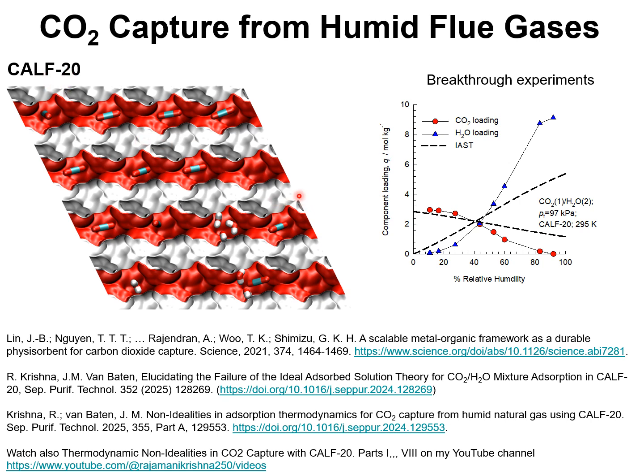CALF stands for Calgary Framework. Furthermore, we note that for percentage relative humidities higher than 45%, there are significant deviations of the component loadings from the IAST estimates, but in this case, the adsorbed phase is richer in water and poorer in CO2 than the values anticipated by the IAST. This is ascribable to strong hydrogen bonding between water molecules, and CO2 faces increased competition by the water clusters that are present in the framework.